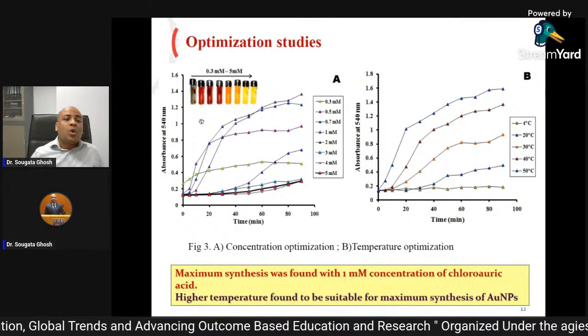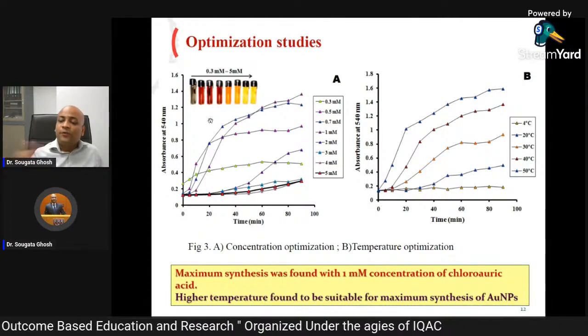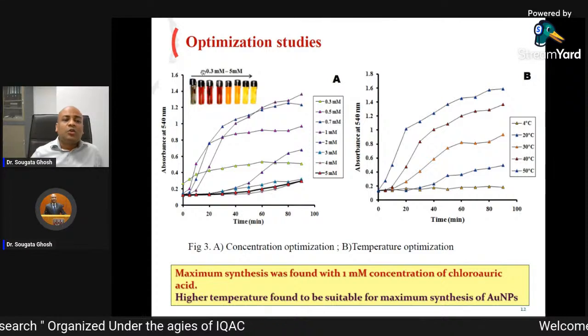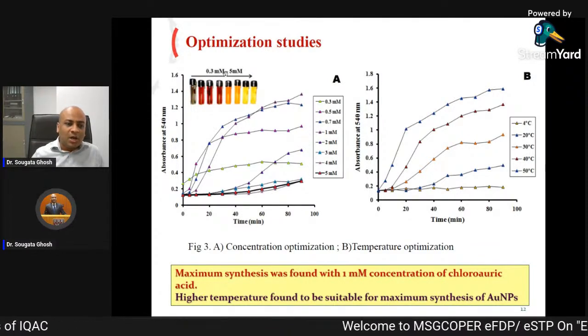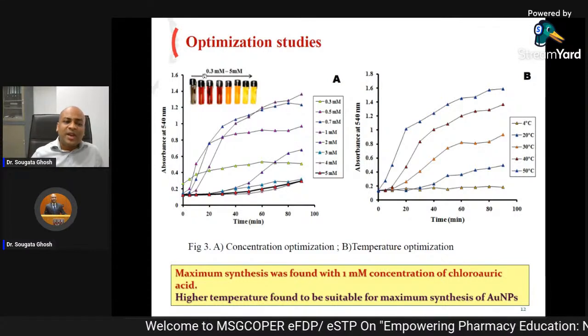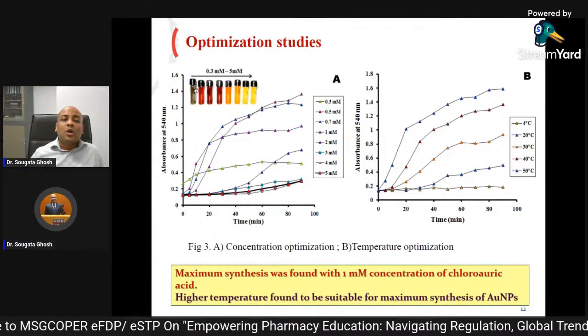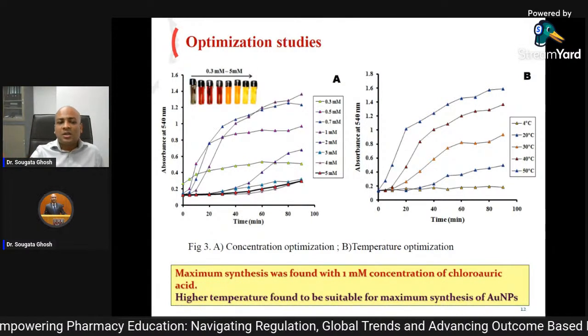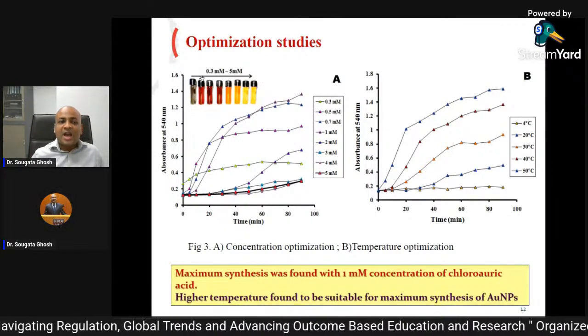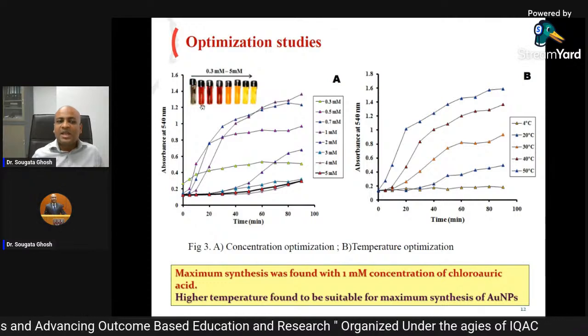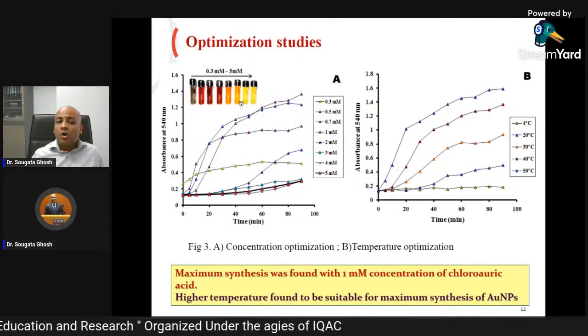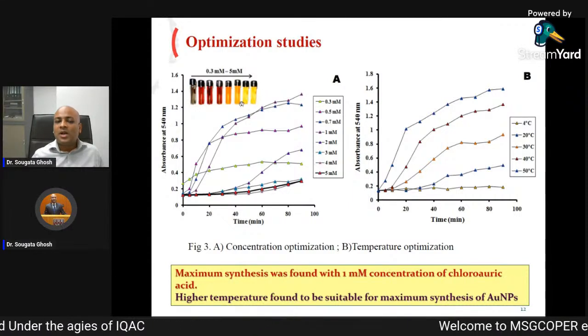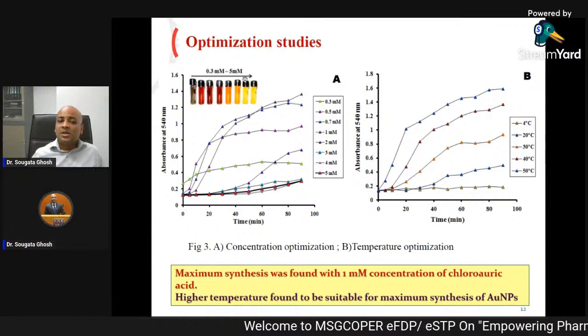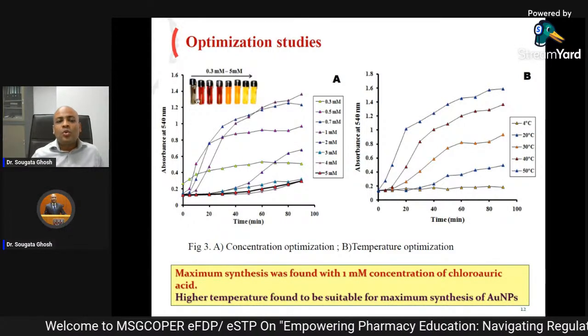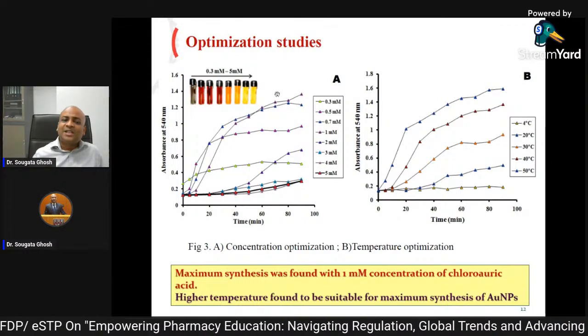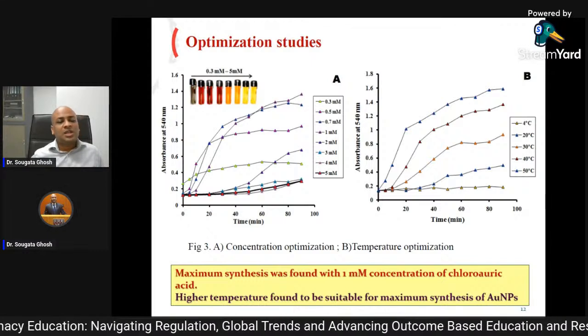Now we wanted to see what are the parameters that can influence the synthesis. So here we varied the concentration of gold salt from 0.3 millimolar to 5 millimolar. And when we varied the concentration, to our surprise, with the same plant extract and the same gold salt, just changing the concentration, colors were different. At 0.3 millimolar, they were gray in color. Then it became red, then ruby red, then orange, and then finally yellow, like gold, golden color. So that means same gold salt, same plant extract, we change the concentration, we get different size of nanoparticles. As the size of nanoparticle changes, the color also changes.